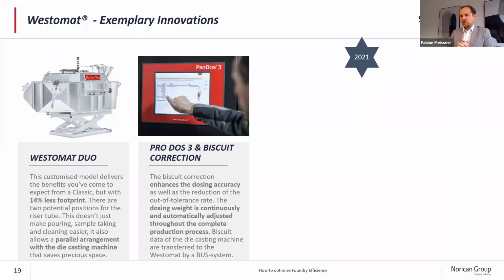We have also released some updates on our ProDOS 3 control. One very classic software feature, for example, is the biscuit size correction. In short, we get a signal from the die casting machine of the size of the biscuit, and based on this size of the biscuit, we continuously adjust the dosing process to make sure that the biscuit size gets reduced, which again reduces scrap.